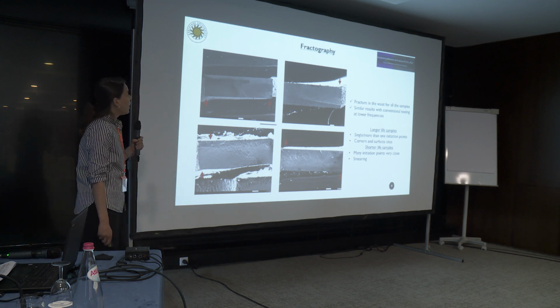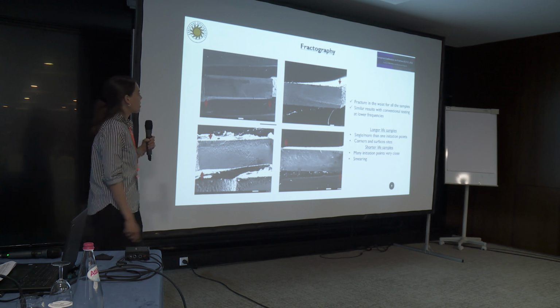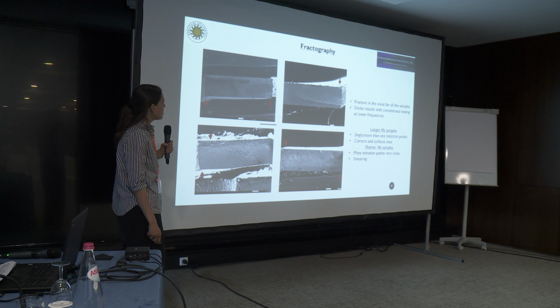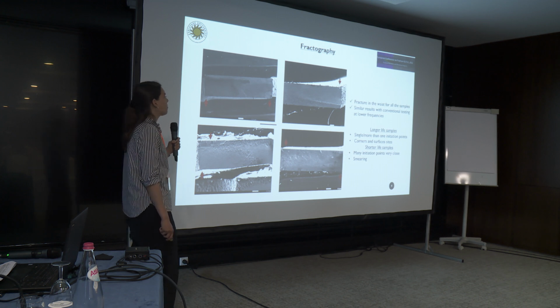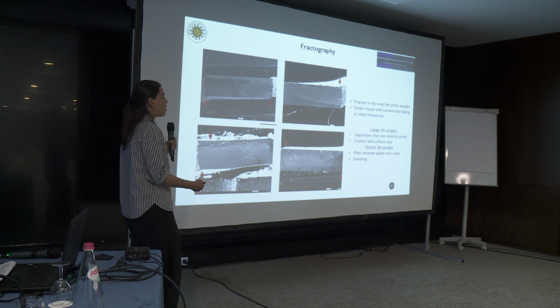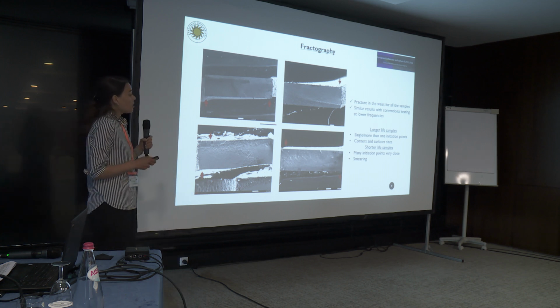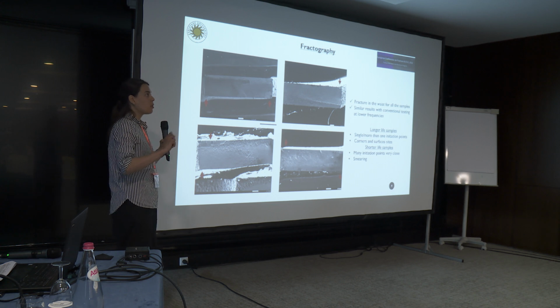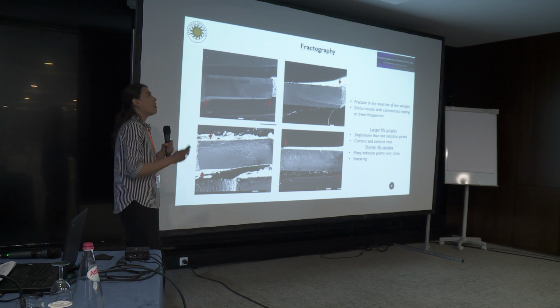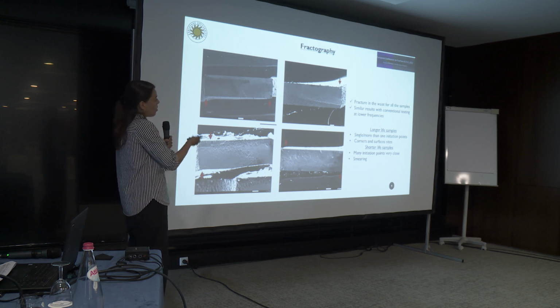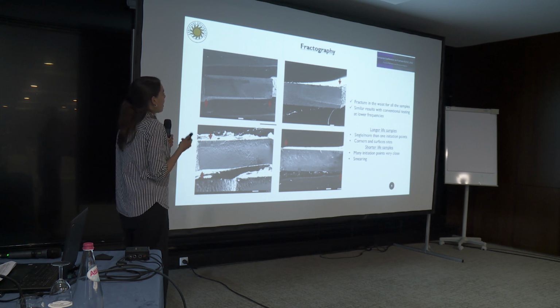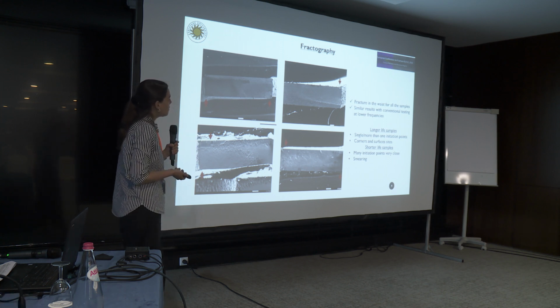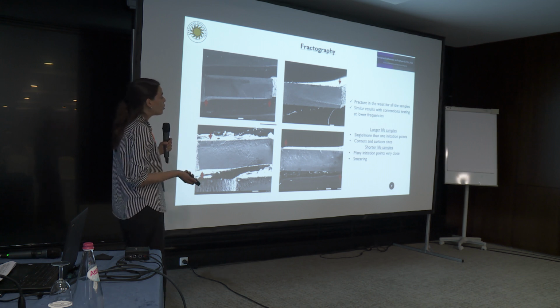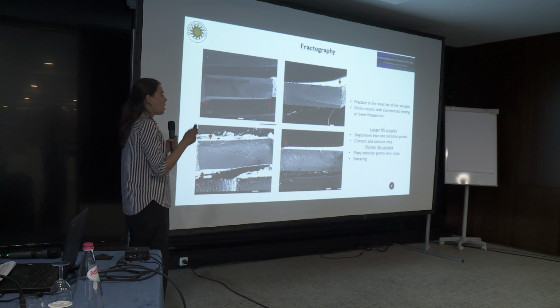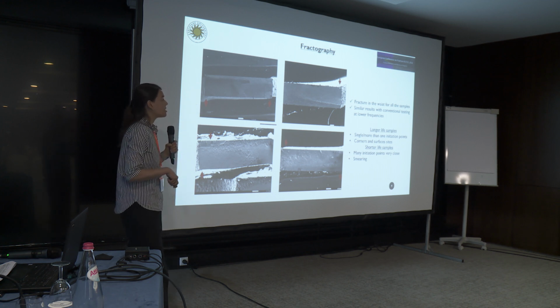So I told you, all of the specimens were broken in the waist. And based on the fractured surfaces, it seems that the results are very similar to conventional testing at lower frequencies. If someone would like to make a clarification between the fractured surfaces, we can split them into longer life samples and shorter life samples. In the longer life samples, usually we had one up to two initiation points, usually at the corners or at the surface sites.